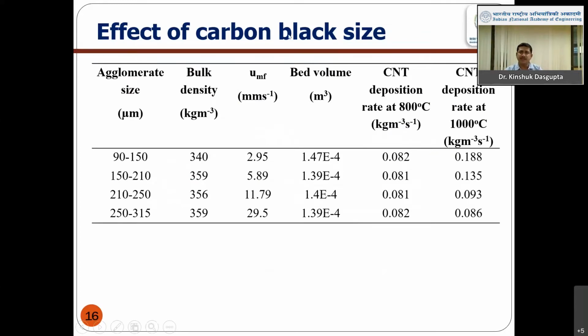Then we change the carbon black agglomerate size. What we could see is that at low temperature there was not much change in the deposition rate, but at high temperature, that is at 1000 degrees centigrade, there was significant change. So we can tell that in the low temperature region, internal diffusion is not affecting, but at high temperature it is affecting, and that is why we got a low activation energy in the high temperature regime.